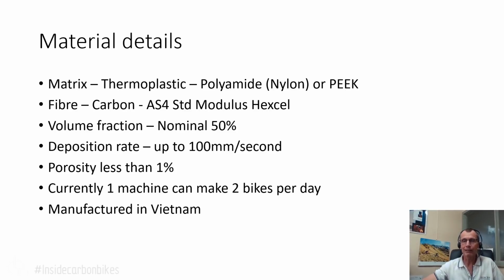Now with porosity, in the white paper and also on their website, they had a micrograph showing that the porosity was less than 1%. So we have to believe that, and if that's the case, that's good. Having a volume fraction of 50% means you've got more of the matrix, so it is easier to reduce the void content because you've got more matrix to fill any potential void. But that does increase the mass and can reduce some of the other properties a little bit as well. But it's good to have low porosity. As we know, air is not very strong.